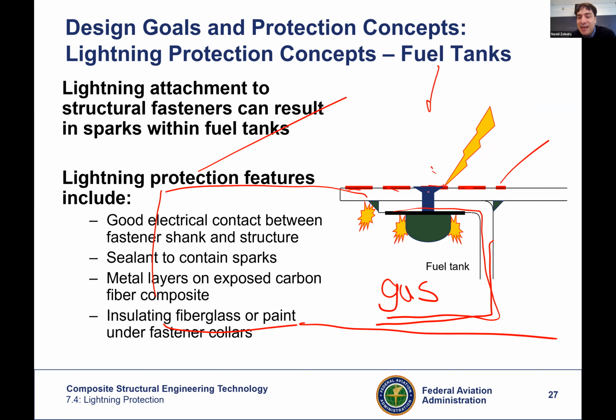The fastener itself is conductive. You have to use metallic fasteners. So it becomes a way for the energy to go toward the gas tank. So you will prevent that by putting a layer of, let's say, glass fiber, which is not conductive, under the fastener. And then you will cover the surface with non-conductive paints, let's say epoxy, which is non-conductive.